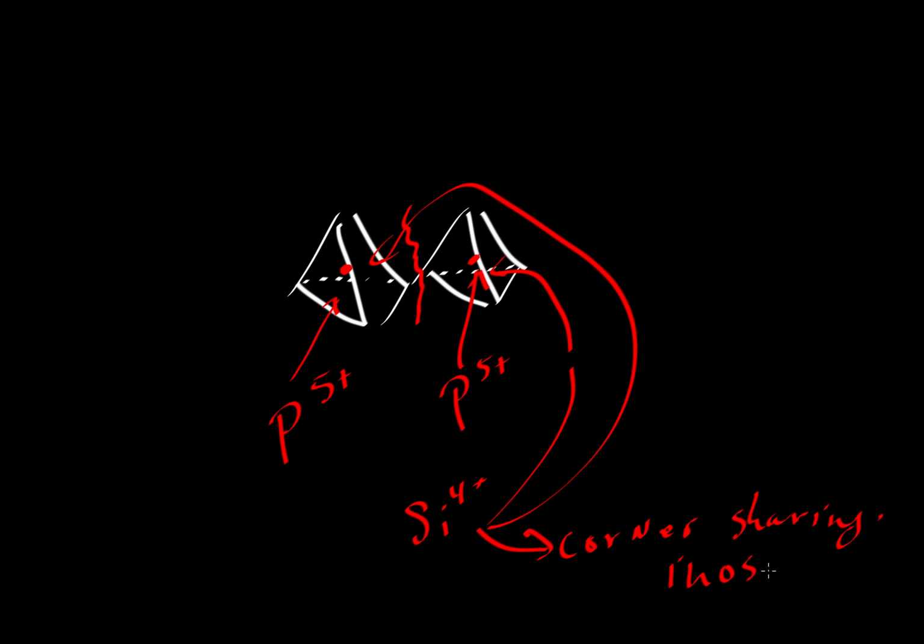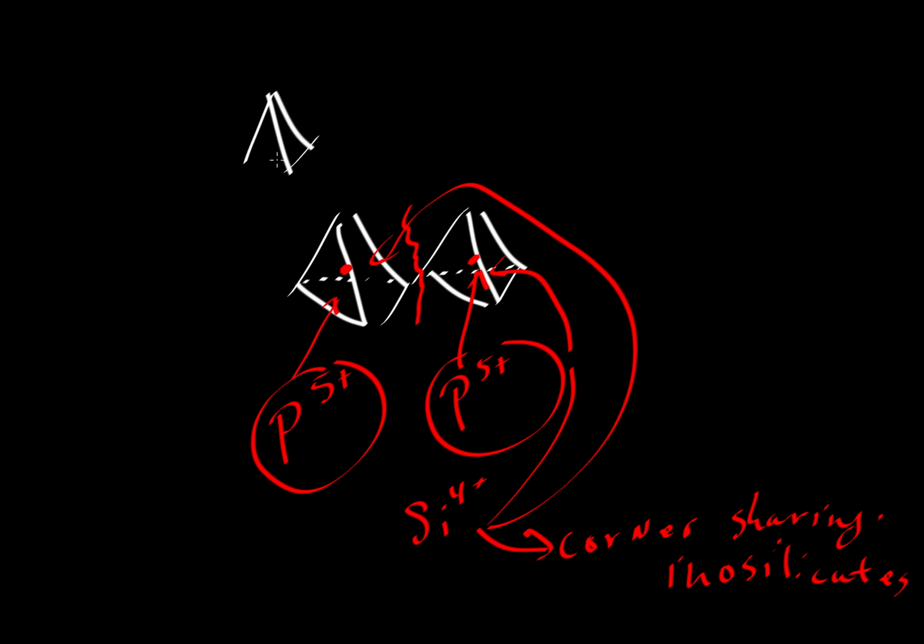So corner sharing is allowed here, and there are many examples of that. The silicates are a great set of examples, but when you get something of sufficiently high charge, like phosphorus in a 5+ state, then even corner sharing would not be likely, and so for the case of phosphorus, we would have separate tetrahedra, as we drew earlier, connected to one another through some intermediary. You can think of, let's say, an octahedron out here, and that would have some other cation in the middle of it.